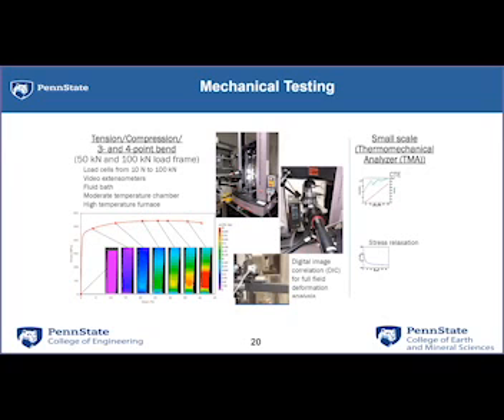We also have mechanical testing capabilities, and one of the more interesting things that we use mechanical testing for is, rather than just pulling tensile bars and looking at an engineering stress strain diagram and trying to measure yield and ultimate tensile strength and ductility and elastic modulus, we use digital image correlation. So we actually will paint these specimens and use some higher end image analysis to allow us to look at localized strain that occurs. Now, when you have different transformations in different materials, we use this widely within my group to understand plastic deformation and the role of potential defects, porosity, lack of fusion, types of things that you run into in additive manufacturing processes.